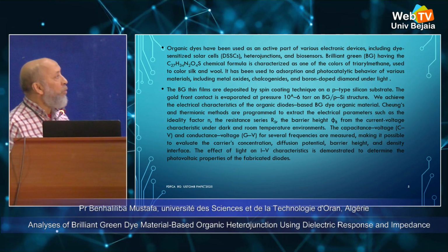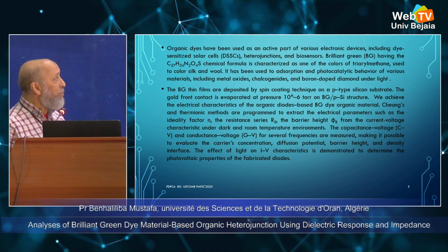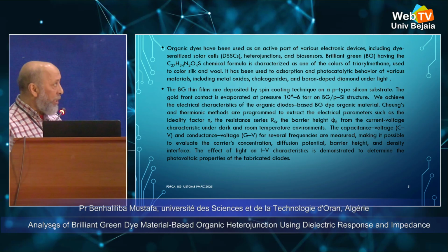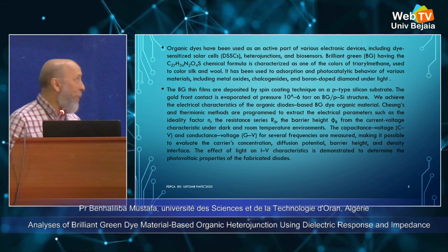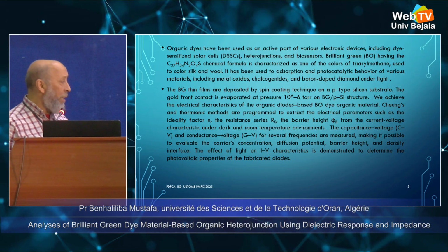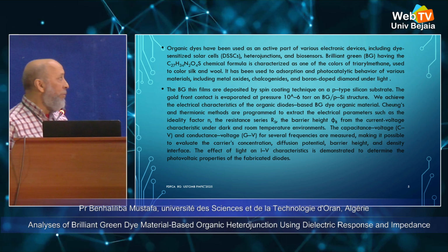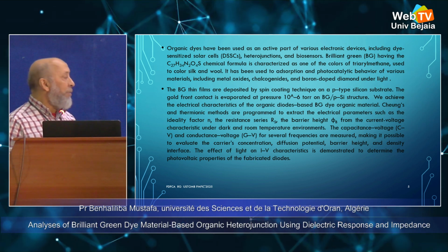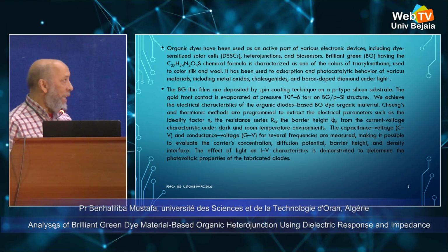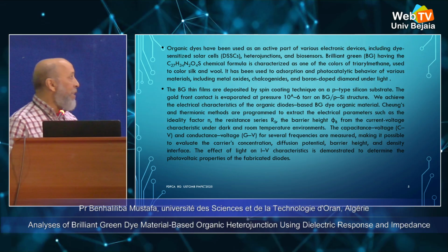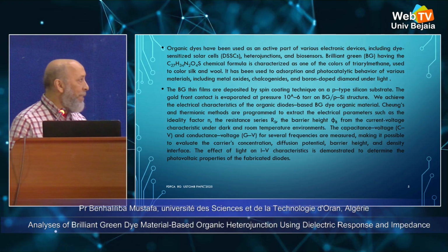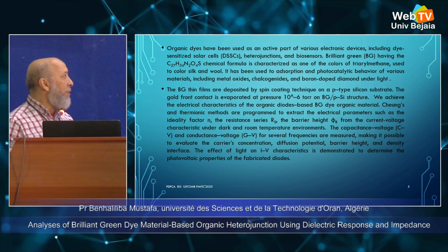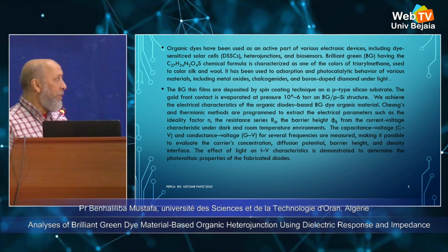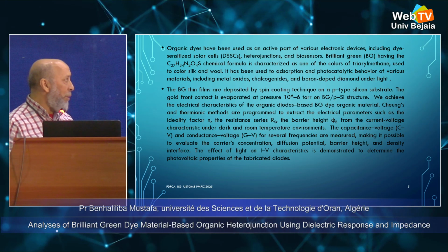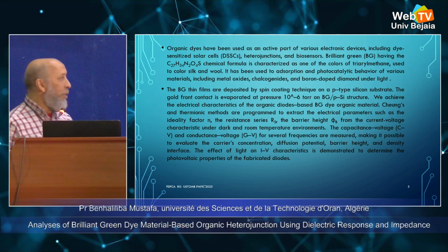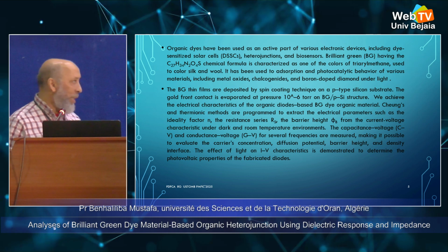It has been used for adsorption and photocatalytic behavior of various materials, including metal oxide, chalcogenide, and boron-doped diamond under light. The BG films are deposited by spin coating technique on a p-type silicon substrate. The gold front contact is evaporated at a pressure of 10 to the power minus 6 torr on the Au/BG/p-Si structure. We achieve the electrical characteristics of the organic diode based on BG dye. Cheung's, Norde's, and thermionic methods are used to extract the electrical parameters such as ideality factor, series resistance Rs, and barrier height from the current-voltage characteristic, in dark and room temperature environments.